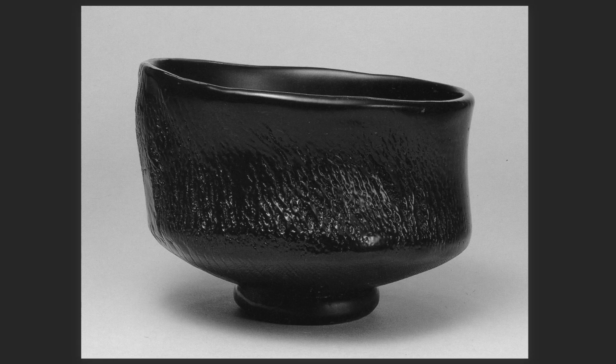Yeah, this has got a lot of texture that you probably can't see, and a black glaze. This might be a hikidashi piece. Hikidashi pieces are treated like raku, but they're pulled out of a kiln on a long rod with a fork on the end that goes under the bowl, and they're lifted out and taken out at about cone 9 or cone 10. And then they're usually cooled in a little box with sawdust in it. Very much in the manner of raku, but at high temperature.